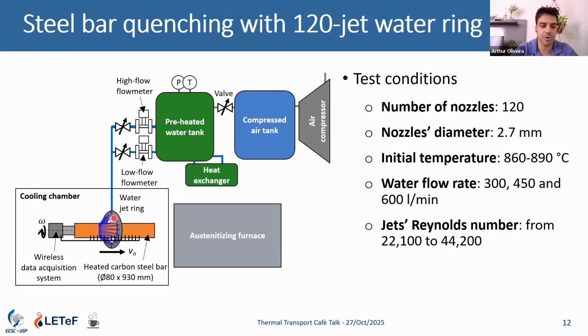The jet ring I'm talking about, I'm going to show you an image soon. We are talking about 120 holes in the water jet ring impinging the bar. They have a small diameter. The initial temperature of the part is quite high, it can be higher in the industrial case, but it's above the austenitizing temperature, so that's enough for the quantification of the cooling process.